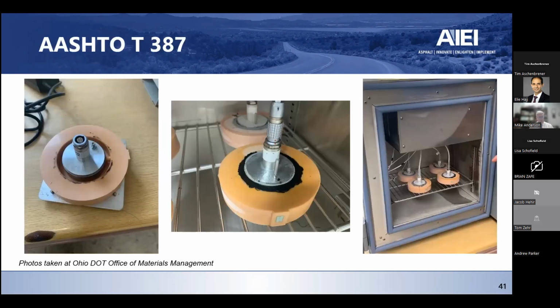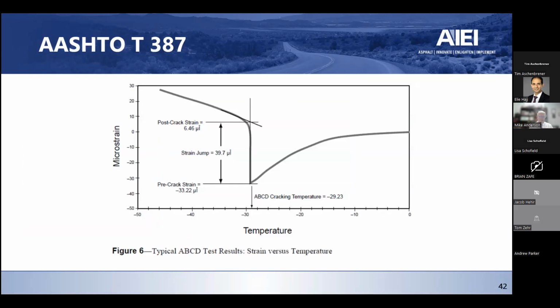This is what the ABCD looks like. We took these pictures up at Ohio DOT's Office of Materials Management. They had a device, and Eric Beal and his team were kind enough to invite us in to see this in operation. On the left-hand side, this is the mold. You can see the gap with the strain gauge in here. We pour the sample in, it goes into a chamber here, and that's where the temperature starts dropping, and we can measure what that strain is. So think of this starting on the right-hand side. As it gets cooled down, it reaches a point where the crack occurs. That's when you see this jump in strain happen, and then you get this post-crack strain that occurs overall. That defines for us what that cracking temperature is, where that jump in strain occurs, okay?